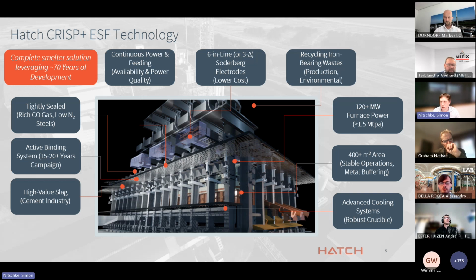The use of self-baking Soderberg electrodes is an important aspect. They allow for true continuous operation of these furnaces at significantly lower cost compared to graphite electrodes that most will be familiar with in EAF furnaces. ESFs also allow for the recycling of iron-bearing waste streams. They're relatively insensitive to alternative feed addition in parallel to the primary feed sources that we're providing to the furnace.